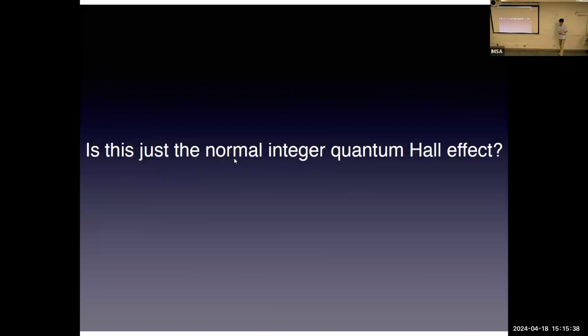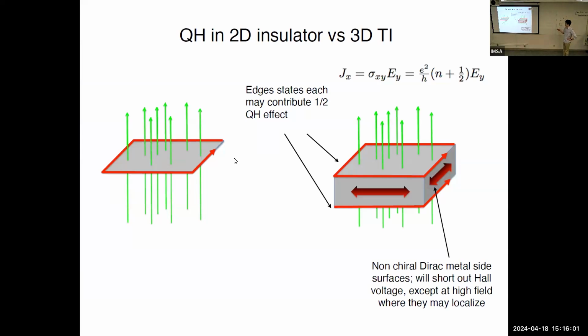And one question people usually have when they read about 3D topological insulators is whether this effect which you observe in 3D measurements is the same as the integer quantum Hall effect, which is observed in 2D electron systems. The answer is no, and there are 2 main reasons. So first of all, 3D TIs have these non-chiral edge states which don't support any dissipationless transport. And in case of just a normal integer quantum Hall effect, you don't have this side edge, which is not gapped. The second, and I think it's even more important difference, is that in case of 3D TIs, you have this 1/2 offset, which is really important. So in case of integer quantum Hall effect, it's just e squared over h.